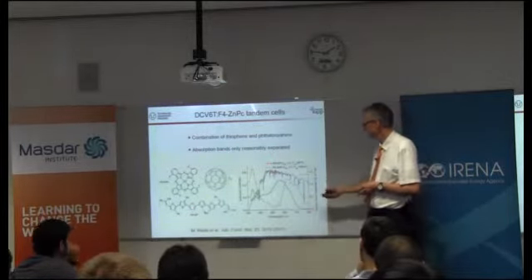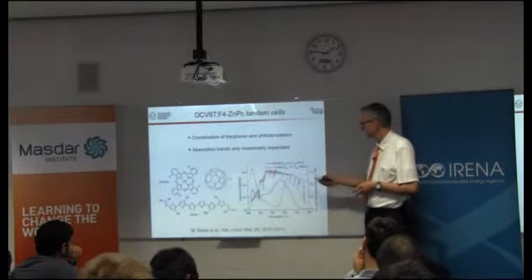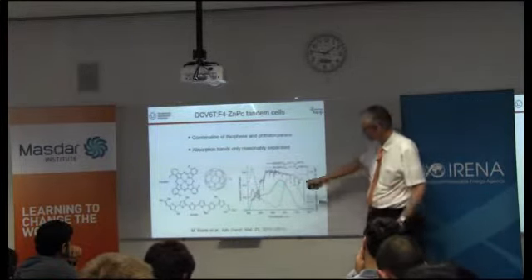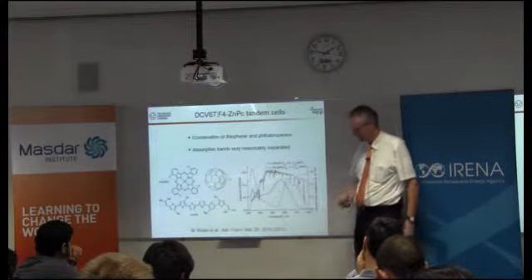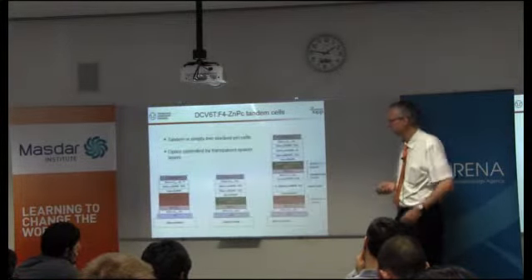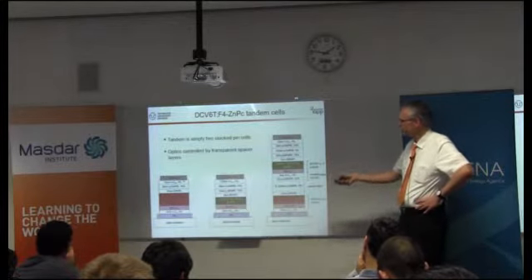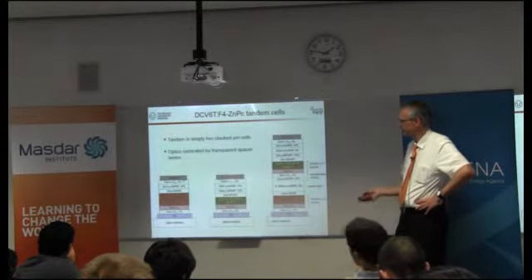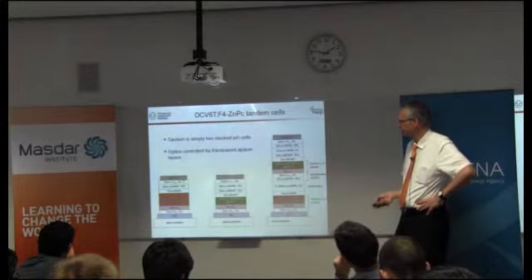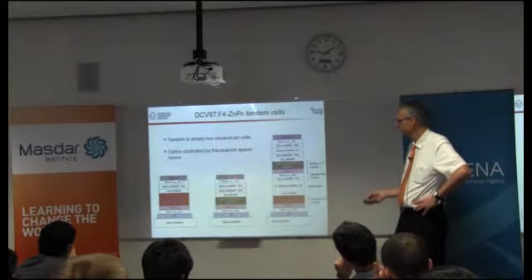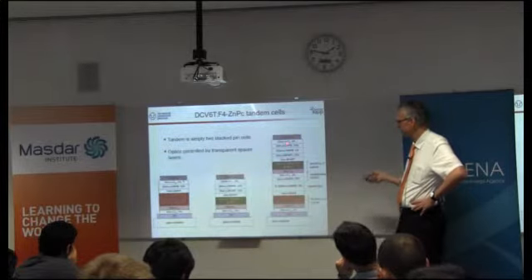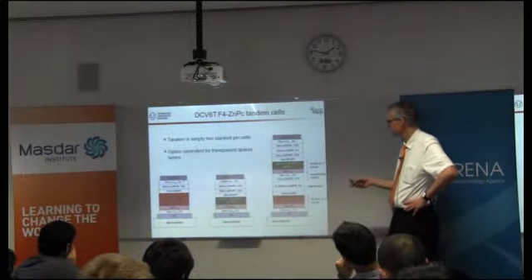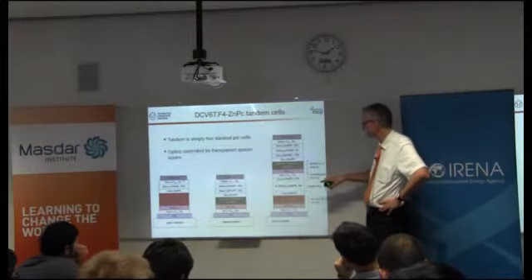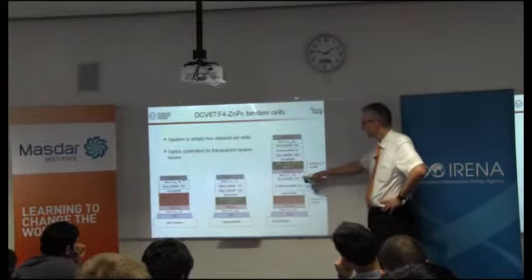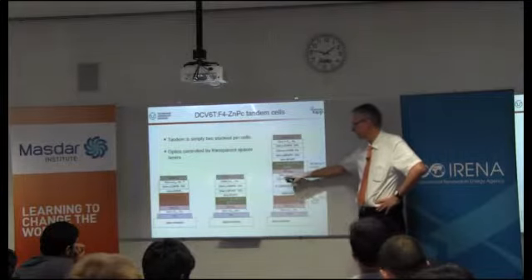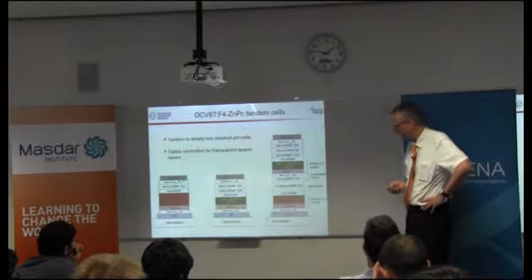The thiophene is again in the visible, and the phthalocyanine in the infrared, although you see there's a large overlap between the two, which is unwanted and should be avoided. And then we make these PIN cells with the doped layers, and as you can see, these are already 6 or 7 layers, the two cells by themselves, or we simply stack the two cells on top of each other. And in that case, you have this recombination junction, which is here, and simply making a PN junction between two materials produces this recombination junction.